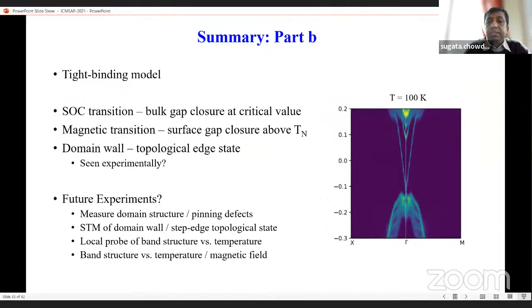So, in summary, the tight binding model we developed matches our experimental results. The bulk gap closes at the critical value, the magnetic transition; the surface gap closes above the TN; and there are domain wall topological states. We are working on understanding what is going on. Future work includes measuring the domain wall structure, pinning the defects, STM on domain walls and steps, topological states, and local probes of the band structure versus temperature and magnetic field. So these are the different works we are focusing on now.